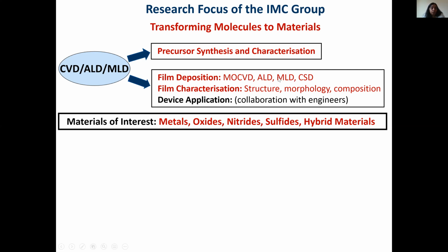And recently we have also gone into molecular layer deposition. That is something to do with organic molecules, similar to atomic layer deposition, where you basically have inorganic materials. Here you can think of molecular layer deposition, coating organic coatings on substrates, or also the cheapest method where you have no vacuum, solution deposition, where you use dip coating or spin coating to deposit films. So we do the deposition. First of all, we synthesize the precursors, we deposit the films using different techniques, and then characterize them in detail in terms of structure, morphology, composition, using complementary techniques.